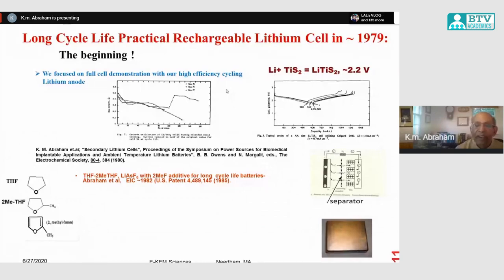So this is sort of the beginning when I started working on it. As I said, there was already titanium disulfide known, but the lithium electrode was not cycling well. So our contribution mainly is in making the lithium anode work well with high efficiency. See, in the battery, you have to have both electrodes work with the same kind of charge-discharge efficiency. So a lithium anode was not working at that time with good efficiency. In fact, it was not possible to charge and discharge a lithium anode more than a couple of times, or maybe 10 times.